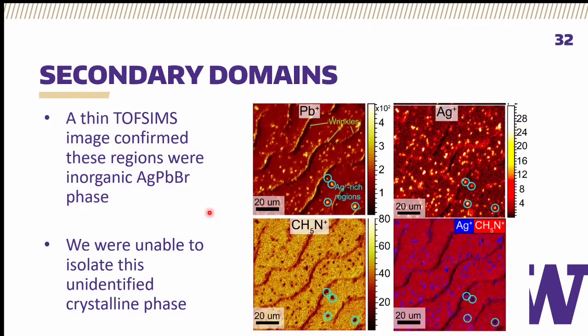But to do a little bit more characterization, we went back to the TOF-SIMS, sputtered off the first 10 nanometers of our film, and then took a very high resolution TOF-SIMS profile of a 1 to 2 nanometer slice of our thin film that was, again, 10 nanometers down from the very front surface. And we wanted to see what the 2D heterogeneity in these different elements was, where we saw that these secondary domains that appeared in, I believe, a 5% silver inclusive sample, were rich in lead, rich in silver, as the EDX spectra previously had shown us, but surprisingly and interestingly lacked any organics at all, any amines, I should rather say,